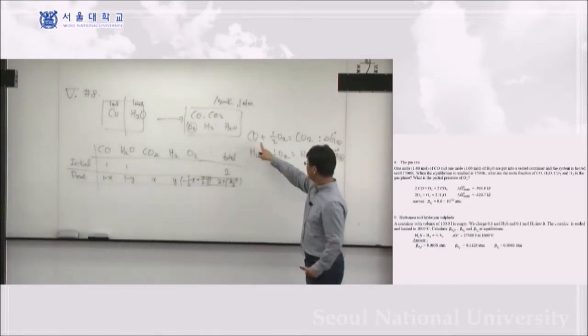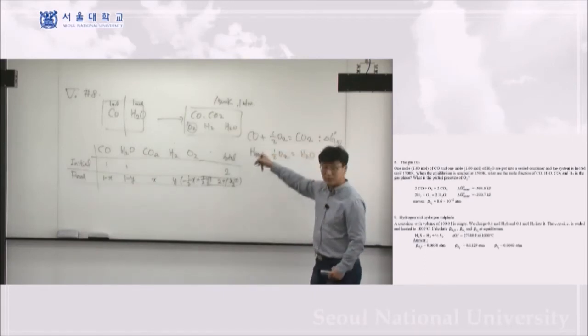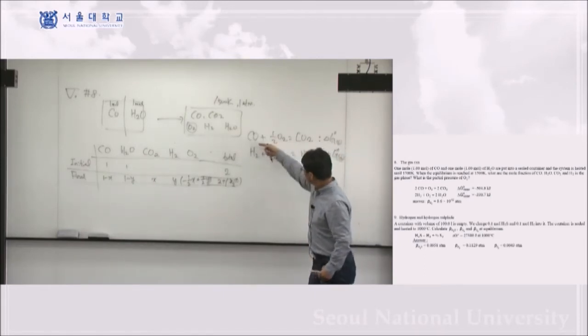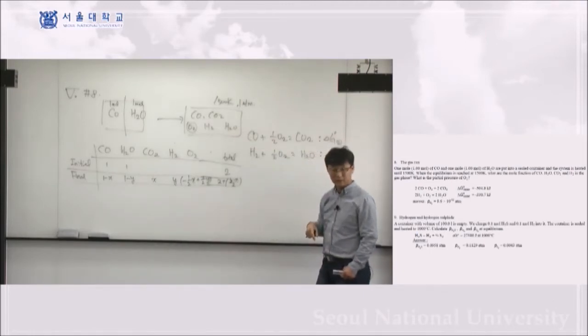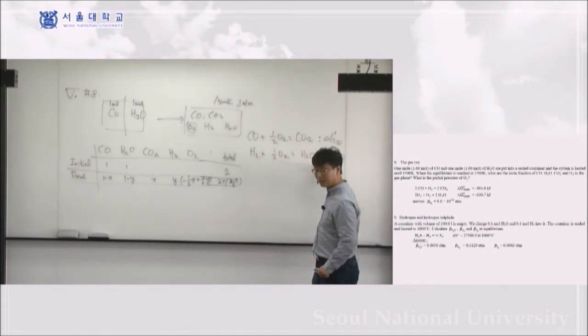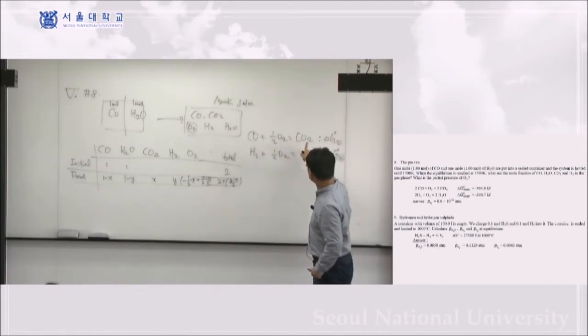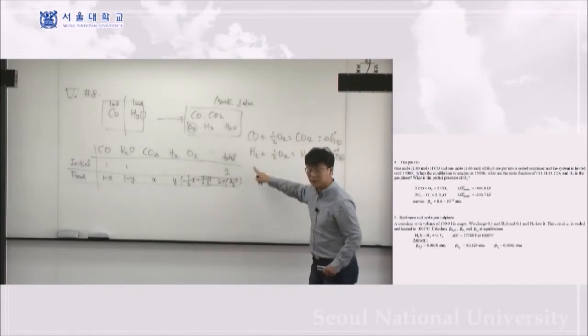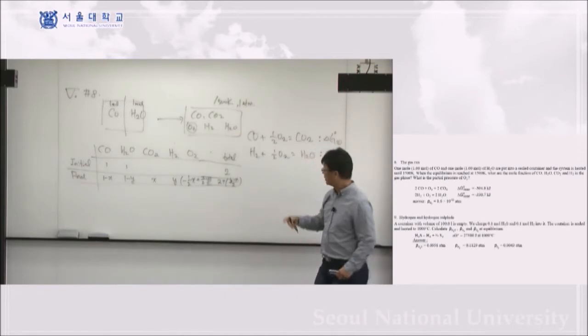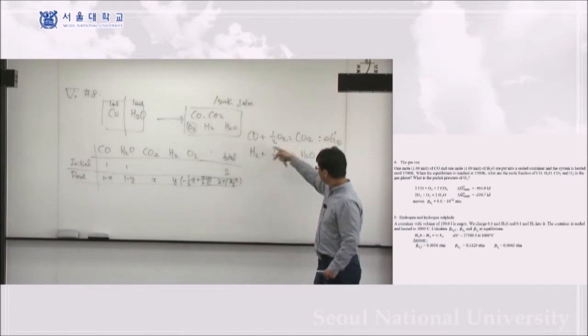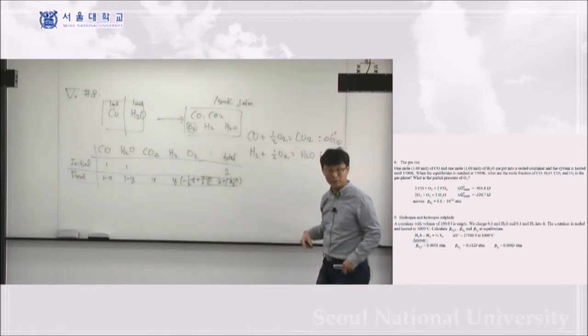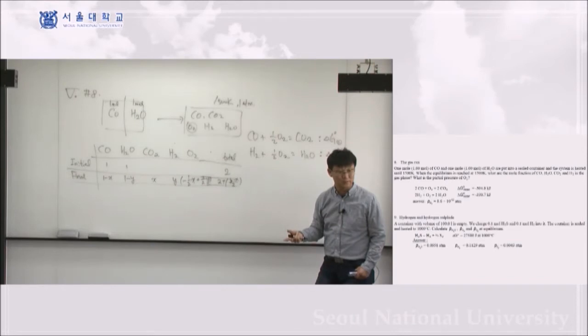So one of the first equations, CO, oxygen, CO2. At the final equilibrium state, this should be in equilibrium too, yeah? This chemical reaction should be in equilibrium. You can take whatever chemical reaction you like, or if you like CO plus H2O become CO2 plus H2, you can generate whatever it is. But these are two independent equations. If you combine them together as one, that third equation depends on the previous two, yeah? It's a combination of the previous two equations. So that's not an independent equation, okay?